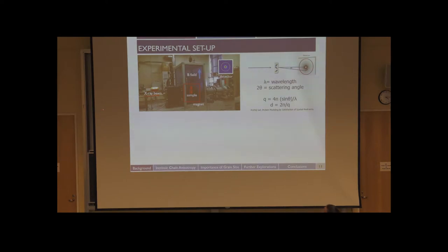For our field alignment, we have a superconducting magnet that can go from 0 to 6 Tesla. For those familiar with MRI machines, those are normally 1 to 3 Tesla, so this is a very strong magnet. The coils are kept at 4 Kelvin — it's a serious piece of machinery that requires a lot of energy input. In this setup, we have in-situ small angle X-ray scattering so we can look at periodicities in our sample in-situ as a function of field strength, cooling rate, or temperature, and analyze the data with a 2D detector.